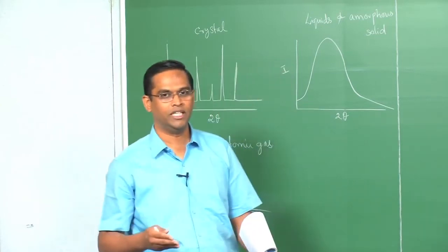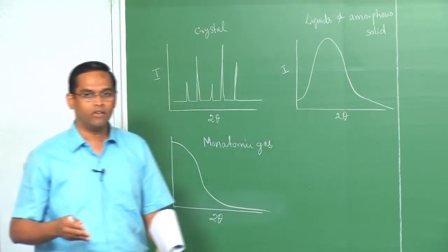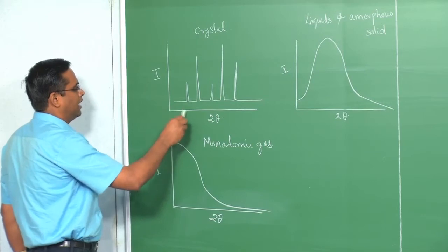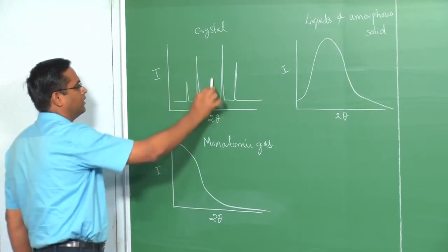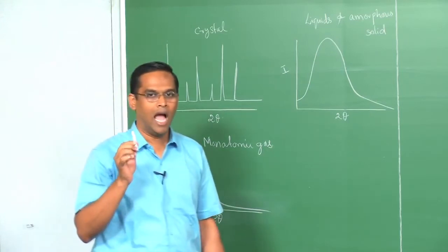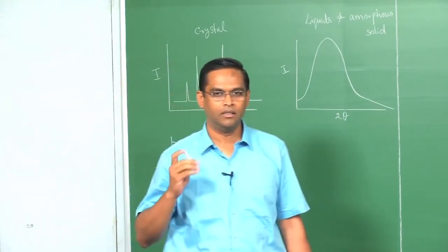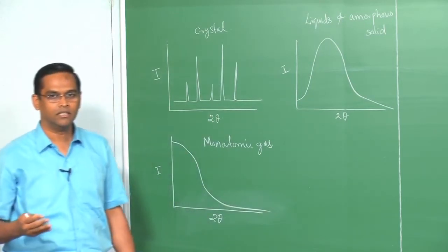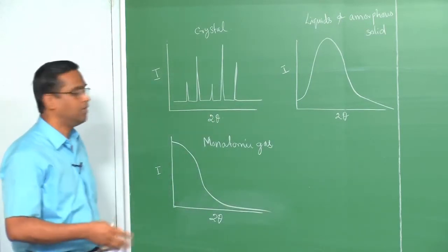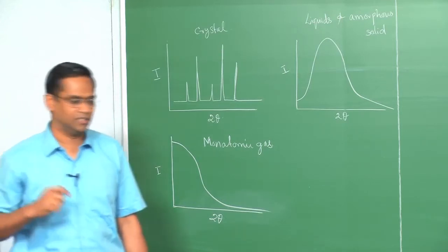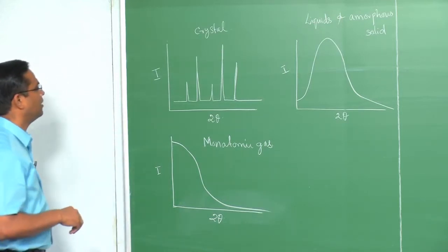You have to appreciate that. The destructive interference plays a crucial role here; the constructive interference happens only at particular angles, that is, the Bragg law, the Bragg angle. In all the other directions it is completely cancelled by all the atoms arranged in a 3-dimensional periodic lattice. So, that is point number 1.